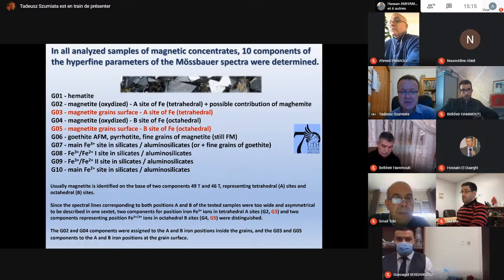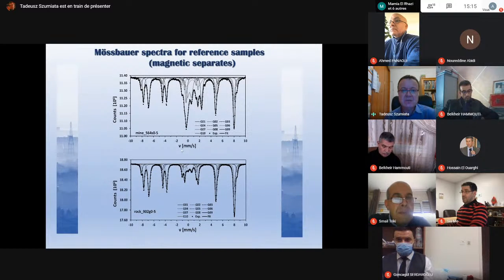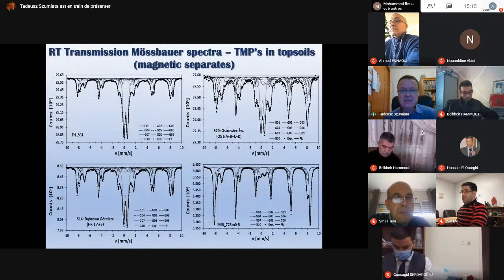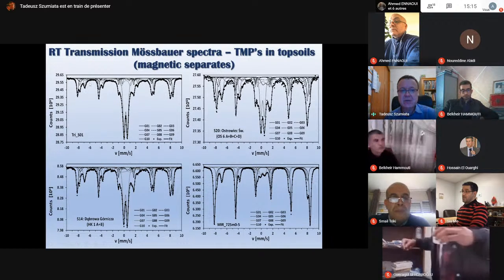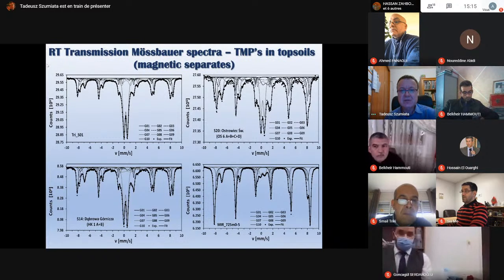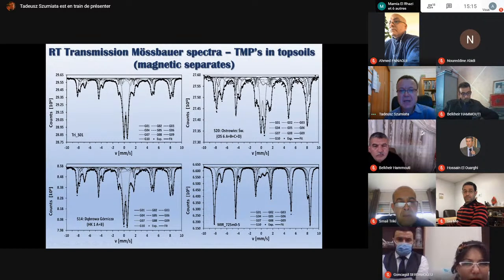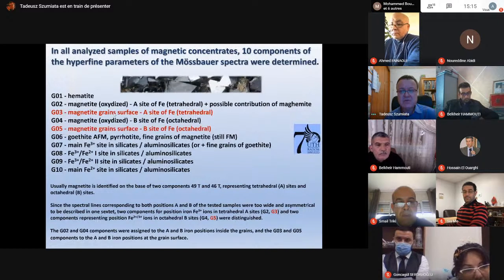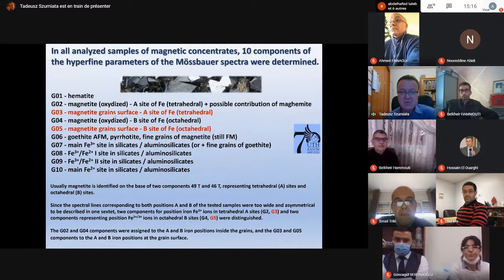What is really interesting here is that when we come back to this spectra, it was impossible to fit this part concerning the magnetite using, as is typical, two components describing A and B sites of iron, tetrahedral and octahedral. It was not enough. It was necessary to introduce some additional, more broad lines, and we interpreted them as a contribution from the surface of very defected grains of magnetite, or maybe it is some new phase related to the magnetite, but very defected magnetite.